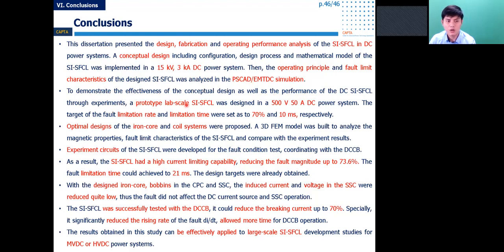a prototype lab-scale SI SFCL was designed in a 500-volt 50 ampere DC power system. The target of the fault limitation rate and the limitation time was set to 70% and 10 milliseconds respectively. The optimal designs of the iron core and the coil system were proposed. A 3D FEM simulation model was built to analyze the magnetic properties and the fault limiting characteristics of the SI SFCL and compare with the experiment result. An experiment circuit of the SI SFCL was developed for the fault condition test and coordination with the circuit breaker.